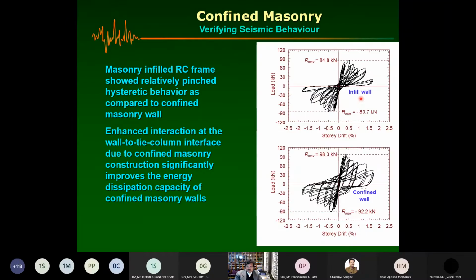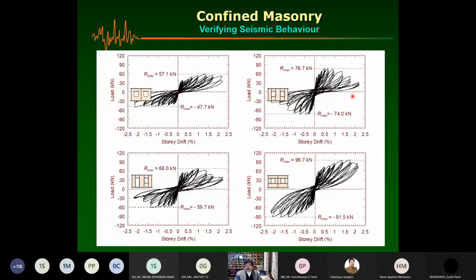Okay. But you can look at the hysteretic behavior. The area under these loops tells you how much energy was dissipated per unit volume. And the important thing to note is that confined walls actually dissipate more energy. They get you more strength, peak strength, and a healthier hysteretic response as compared to your infill walls. And even with the openings, you see that this is the conventional infill with the lintels. You can see the strength levels. But if it's well confined all around, you get to 96.7, 91.5. This is the same as for the solid walls.